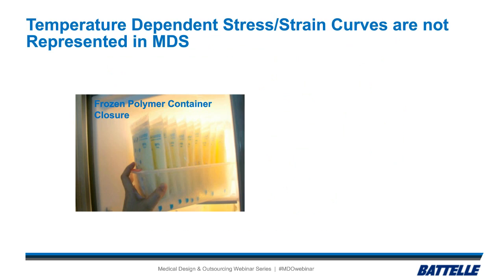Next, I'll go into some more detailed examples of where these material data sheets may come up a little bit light on information. So usually you do not have temperature-dependent stress-strain curves represented in a material data sheet. So if you think about a system that's frozen, so again, we're probably testing at room temperature, 23 degrees C, but our material, which is the bag in this picture, holds a high-value liquid, and we know that the elongation at yield is one number on the data sheet, but as you get colder and colder, that number becomes lower and lower.